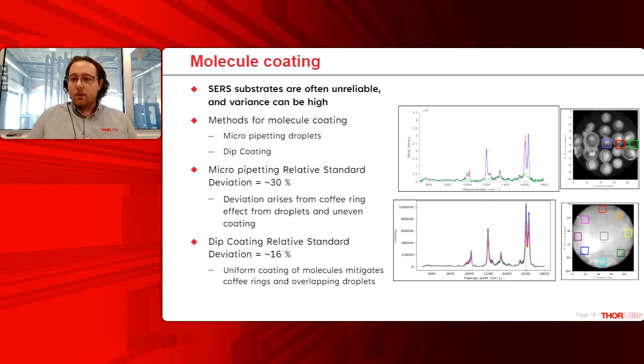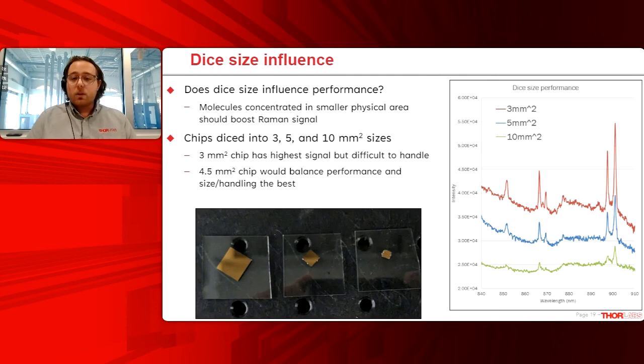So now that we have characterized our uniformity on the wafer scale, we do need to dice them into substrates. So how do we pick what size substrates? That seems to be a common issue with different substrates out there. How big should they be? In this case, we ran some tests to see how dice size may influence the performance of these SERS substrates. A thought experiment we ran was that if you have a customer who is micropipetting the droplets onto the surface of a SERS substrate, if you have a fixed volume of molecules and you place it onto a smaller area, you would get a higher signal. If you think about it, if you place the fixed droplet size on a larger area, those molecules are going to spread out more and they will kind of self-dilute across that surface.